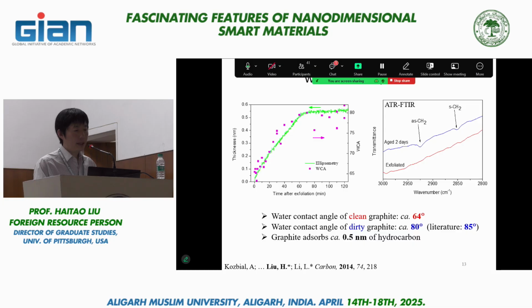You may notice that in the case of graphene on copper, the initial contact angle is around 42 to 45 degrees. The initial contact angle here is different. It's 60. And what's the difference? The difference is the substrate. In the previous case, the copper underneath graphene is actually making an impact on the overall wettability. So that is a concept of wetting transparency, and I hope I'll have more time to discuss that tomorrow.